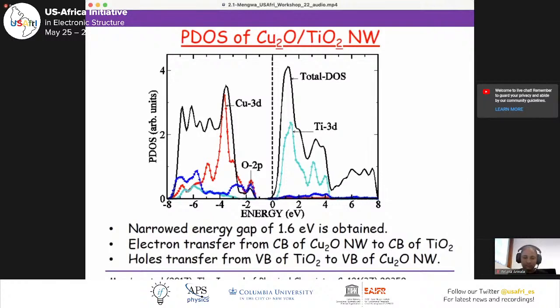Now the PDOS of the cuprous oxide/TiO2 nanowire is shown here. You see that the energy gap has been narrowed to 1.62 electron volts, and this is because states have extended into the energy gap.